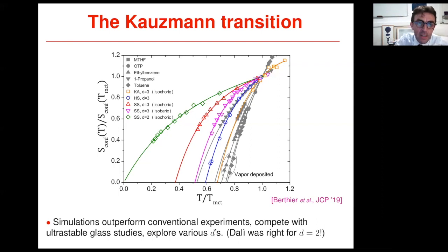So there is one guy here which is a little bit different, which is the green one. So the data here are obtained for a glass simulated in 2 space dimensions. So clearly it behaves differently from the others. So the data suggests that if you do the Kauzmann extrapolation of where this entropy is going to vanish, it's going to vanish very close to 0 temperature, suggesting that this ideal glass phase where the system transforms into a glass does not exist for 2-dimensional systems. So it seems maybe that Salvador Dali was right after all when he claimed that perfection would never be reached. At least he was right in 2 dimensions.